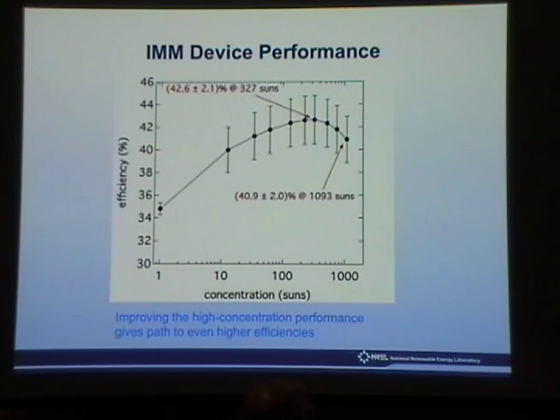And there's a lot of work on minimizing this rollover. Obviously increasing the whole magnitude of the curve, shifting it upward to begin with, but also decreasing that rollover. If you can maintain a high efficiency at 1,000 suns, you use half the material that you would need if you were at 500 suns. So again, it's a cost leverage in terms of the system.